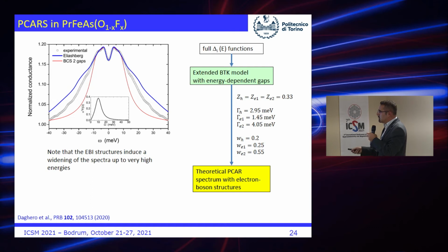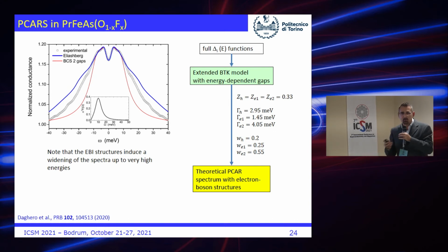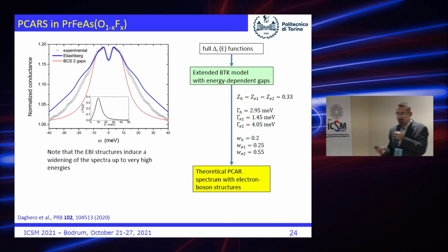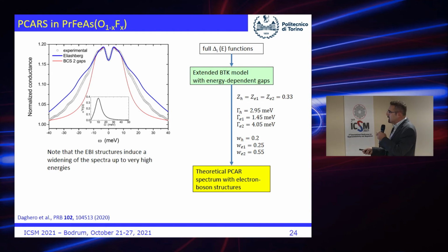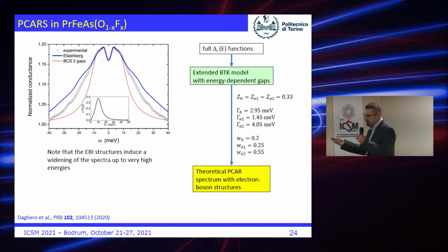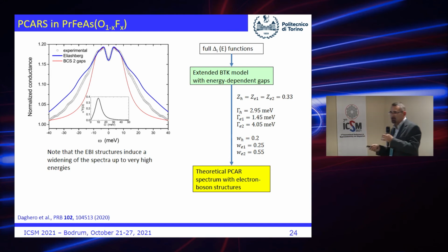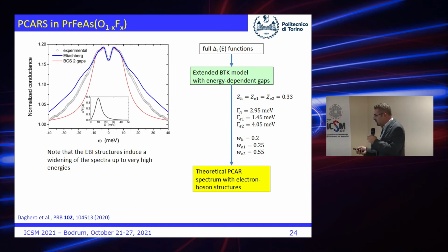This was the gap, the fit with BCS. Okay, this is instead not a fit. It's just a calculated curve that more or less resembles this one. But you see that this usual excess conductance is reproduced. Clearly, for those who work in the field, with a slightly different normalization I could obtain the curve that is exactly this shape. But we did not do that expressly, so as not to trick.